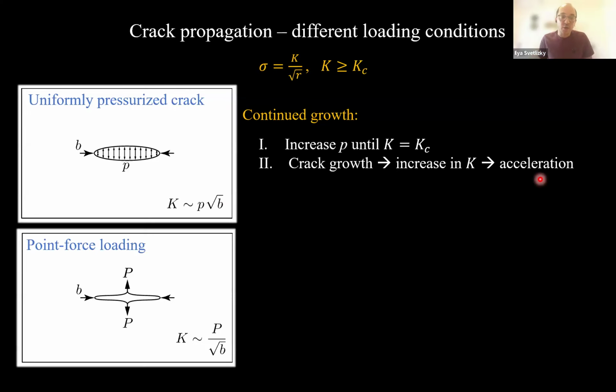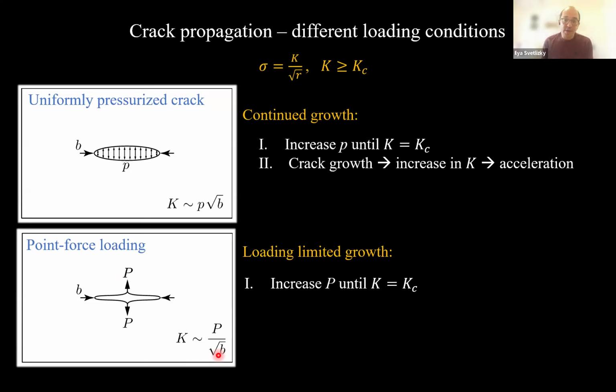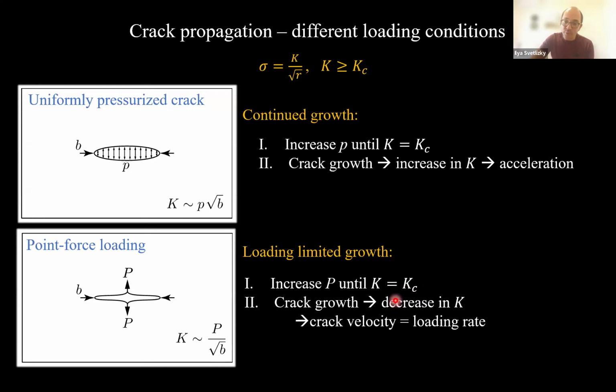Good. A different scenario is if you imagine point force loading. Again, you have an initial seed crack with a length B, and you apply point forces. In this case, the stress intensity factor K will decrease as the square root of the length. So again, you start with some initial length B, you increase your point forces until K reaches the critical toughness, and the crack will start propagating. But this time, as the crack propagates, K is decreasing, and in order to keep the crack propagating, you need to increase your forces, meaning that the velocity of your crack will depend on the loading rate, or how fast you increase P.